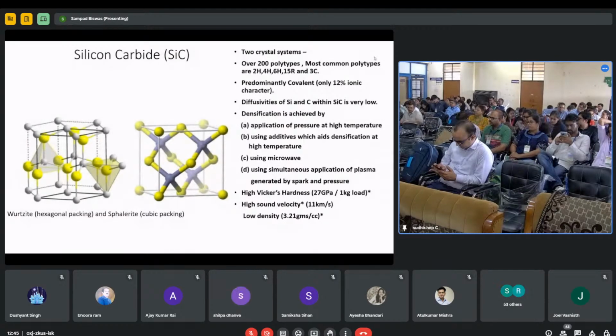the structures. Now, one important thing is that since these are covalent, the diffusivities of silicon and carbon within their lattice are very low. So you have to apply pressure, high temperature and additives to prepare these polycrystalline materials. Now we are dealing with the polycrystalline materials. We are not dealing with the single crystal materials now.